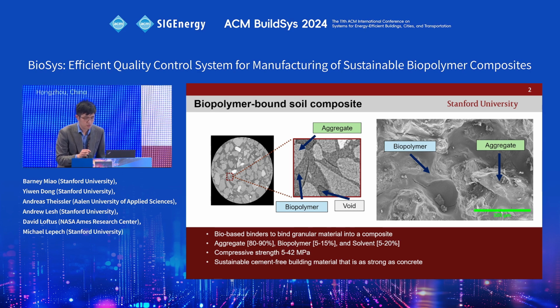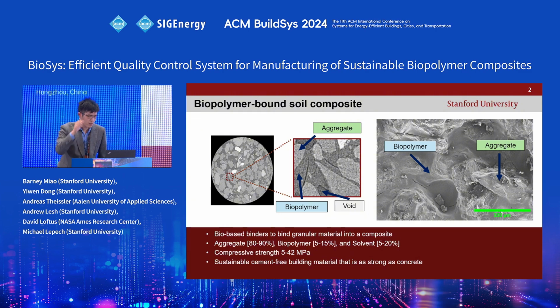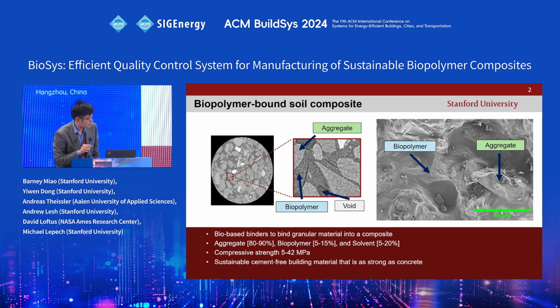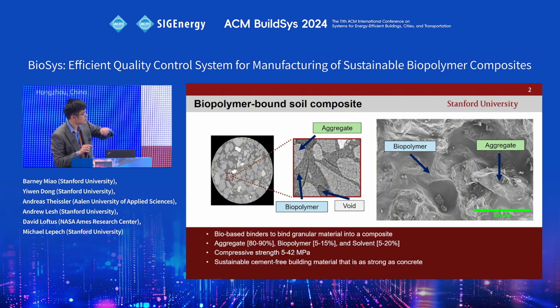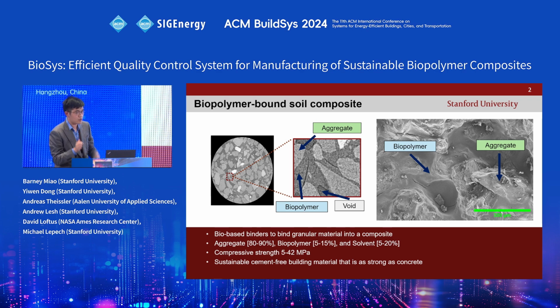In this case, our research group develops something called biopolymer bound soil composites, which uses nature-based biopolymer waste binders to bind together a granular material into a solid composite for building. You can see here in the micro-CT scan that you have a biopolymer matrix that binds together the aggregates, and you have voids also in the resulting composites. And you also have the SEM image where you see the biopolymer binder tightly binding together an aggregate, forming your composite.